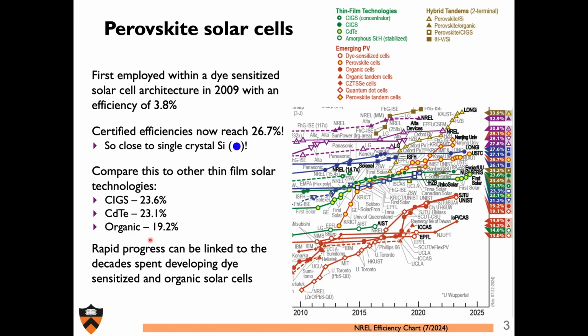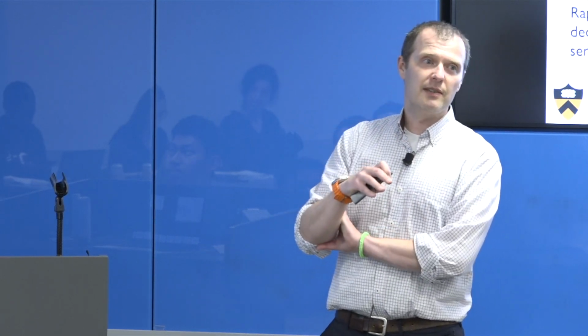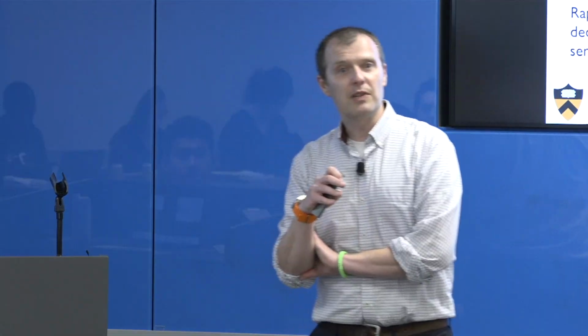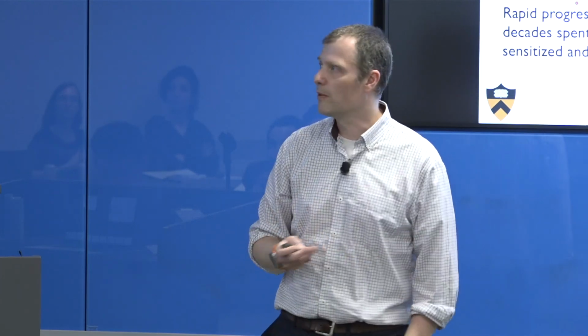on day 0. The issue with perovskites, and what brings me here today to talk to you about, is not in their initial efficiencies, but rather in the fact that those efficiencies don't hold for an excruciatingly long period of time. For most solar technologies, you want that to hold for decade timescales, and that's indeed what silicon can do. But perovskites, the best they've demonstrated, is somewhere in the neighborhood of a few thousand hours for degradation from its day 1 value to about 80% or so of that initial performance.